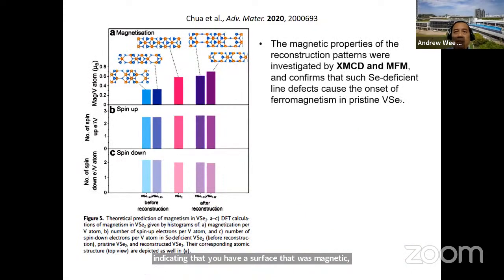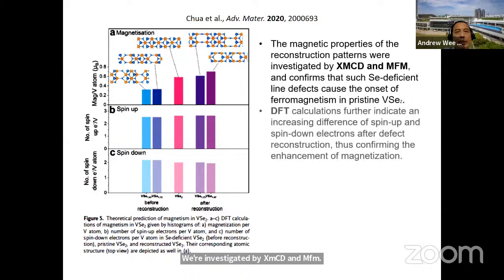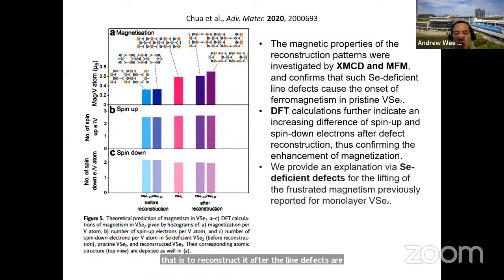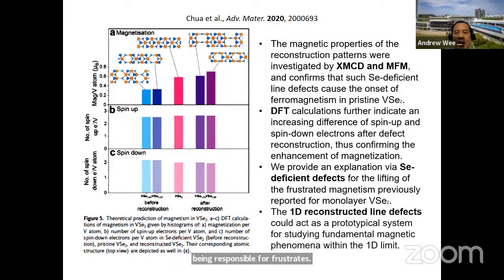So the magnetic properties of our reconstruction patterns were investigated by XMCD and MFM, and we also did DFT calculations. And we showed that if you use DFT calculations on a structure that is reconstructed after the line defects are formed, you have an increase in magnetism, which is consistent with our observation. So hence, we provide an explanation for this selenium deficient defects being responsible for frustrated magnetism. And this could be a prototype system for studying fundamental magnetic phenomena within the 1D limit.